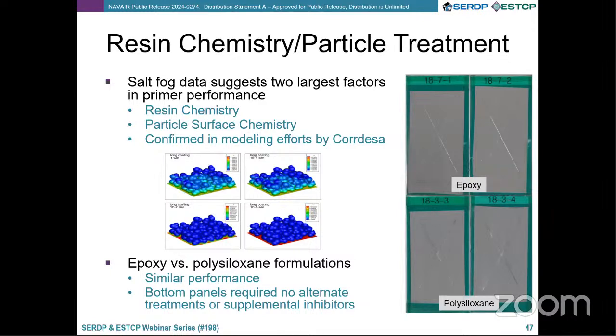A lot of that work was validated later on by modeling that we put out on an SBIR contract, and Corrdesa as a company was able to show through electrochemical models, by which they built out a geometrical representation of a film and then changed a lot of those characters. The electrochemistry of the anode alloy and pigment itself, the surface chemistry of it, you're able to measure in a simple flat cell, as well as the electrochemistry of the resin. And so they were able to confirm what we had learned through iterative experiment. And that was really helpful to learn. Because of that, we learned that the biggest contributors to the performance of the film are the resistance, or effectively impedance, of the resin matrix, as well as the size, contact of the particles and the surface chemistry of them.